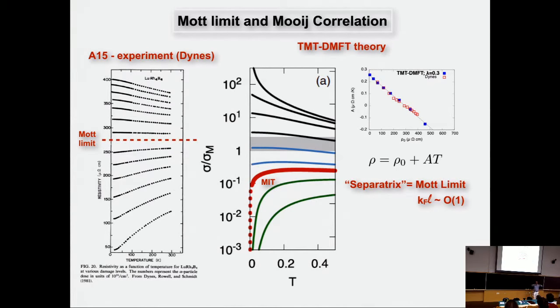in fact, there is a form of phase separation that happens at strong disorder in a disordered superconductor, and that's a rather subtle effect. So I'm not so sure if all these subtleties, which are specific to the superconductor, can be captured in such a simple picture as this one, but definitely some trends of this type probably can be captured, I assume. Of course, we have not done this yet, but I think that's an interesting direction to think about. Okay, more questions?